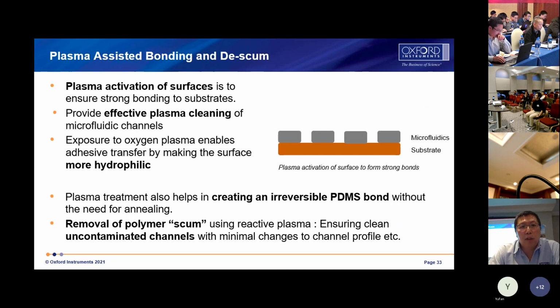So plasma activation of the surface is to ensure strong bonding to the substrate, and provide effective plasma cleaning of microfluidic channels. The plasma on, then another wafer bonding on the surface. Exposure to oxygen plasma enables adhesive transfer by making the surface more hydrophilic. Plasma treatment also helps in creating an irreversible PDMS bond. I think the other talk from Nanjing Professor Han already showed lots of interesting structures based on PDMS. This method works without any anneal.